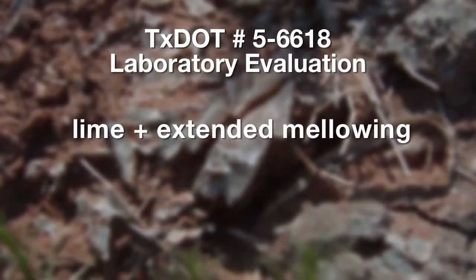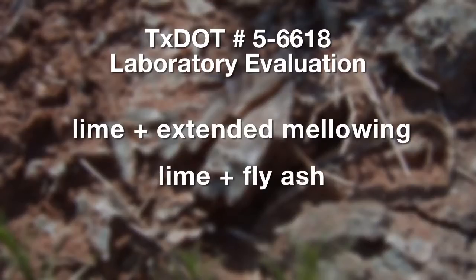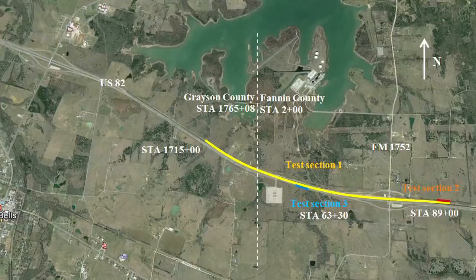In the lab, we looked at different treatment methods. The two treatment methods, one of them is lime with extended mellowing. The other thing we did is cut down the lime and add fly ash. And both of them showed good promise in our lab studies. So from the lab, we go into the implementation where we have test sections at one of the projects at US 82 in Grayson County in that area.